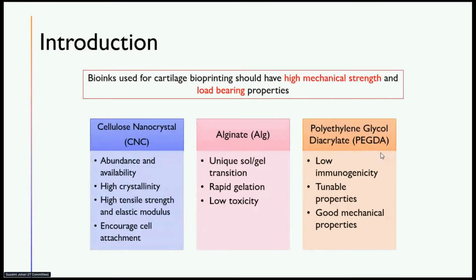And the second biomaterial is alginate. Alginate has a unique solid gel state, which allows the formation of a hydrogel network using the cross-linking by calcium ions. And the fast gelation rate that alginate has also makes it suitable for extrusion bioprinting. Alginate is also widely used as a biomedical product because of its low toxicity and good biocompatibility.